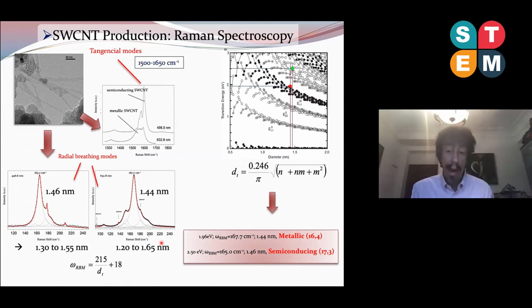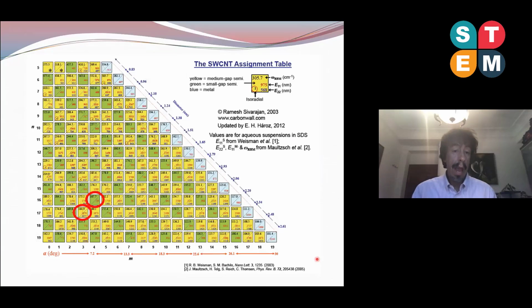We have identified specific metallic and semiconducting nanotubes, and these are all possible carbon nanotubes, and you can see how close in diameter they are. And among all possible nanotubes, we identified two different single-wall carbon nanotubes which are almost identical in diameter, and this is, I think, a remarkable result.